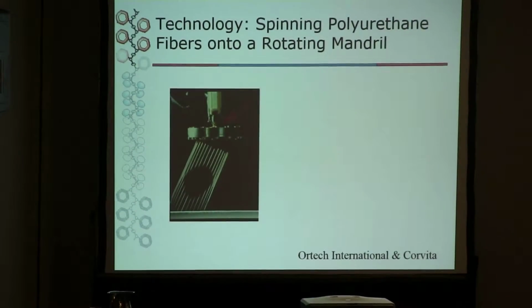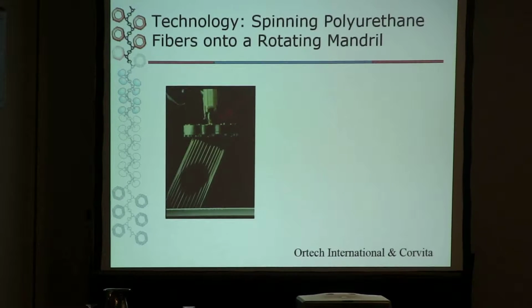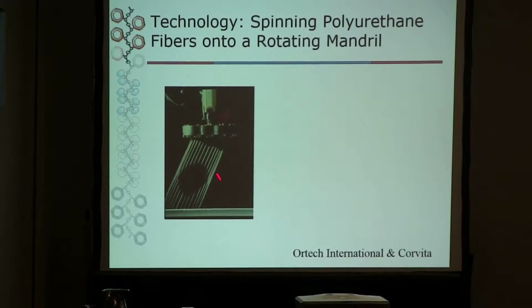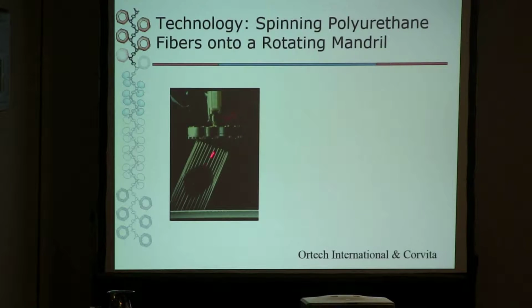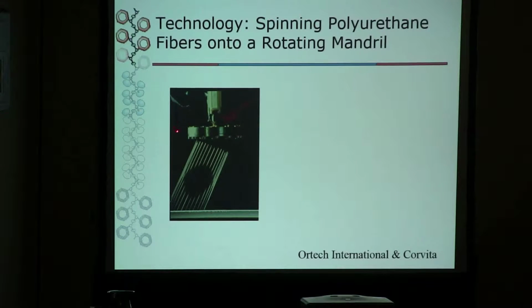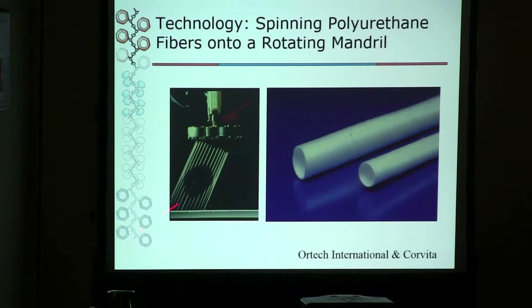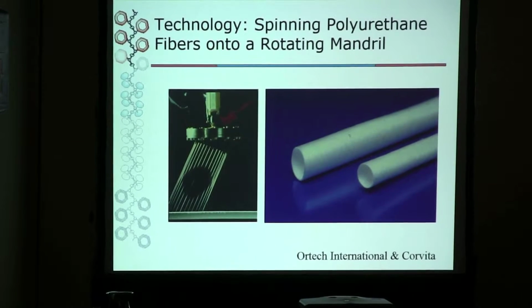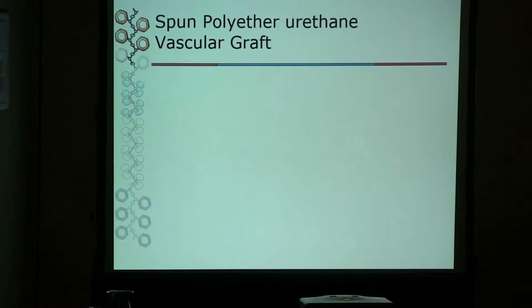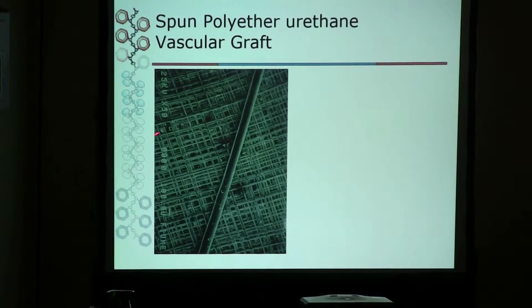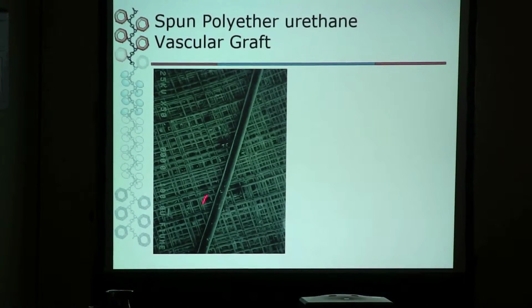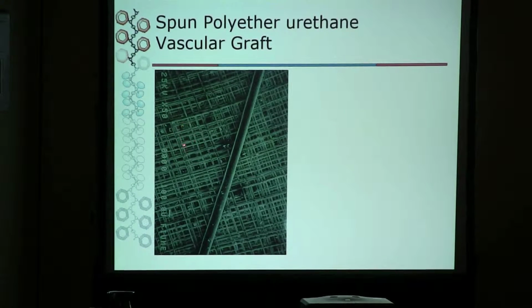And the technology that we worked with was a spinneret, which you see over here, and we have 30 fibers coming out of it, and the fibers and spinneret were moving to the right, and they go back and forth hundreds of times to build up a porous matrix. And if you take the porous matrix and you pull it off the mandrel, you have this vascular graft with controlled porosity. And this is the fibers over here relative to a human hair. So they were 20 micron fibers and maybe 20 micron pore size.